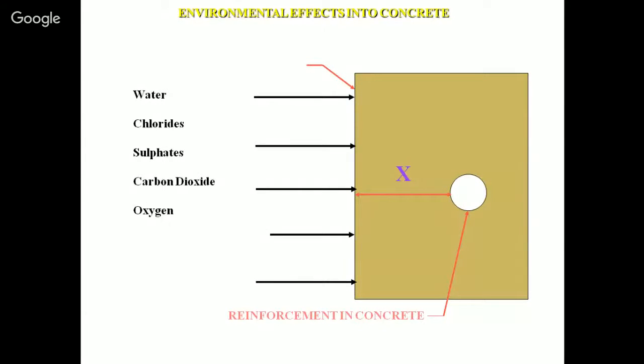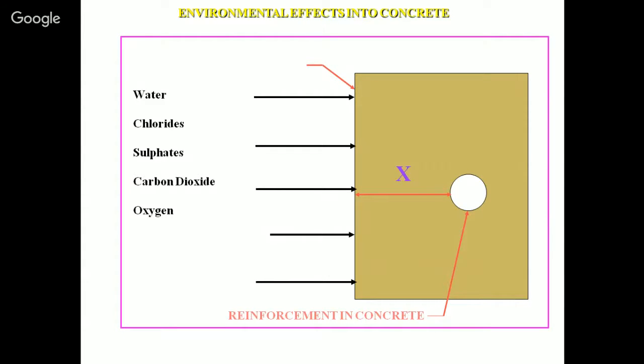This particular slide shows that one of the factors responsible for deterioration is the permeability of your concrete. If there are more pores, more permeability, or more moisture ingress into the concrete, it will lead to further reactions in the concrete, and those reactions will ultimately lead to corrosion. That causes the breaking of the bond between steel and concrete, and ultimately leads to failure. You can always relate corrosion to cancer in a human being: corrosion in a building is just like cancer, very difficult to take care of.